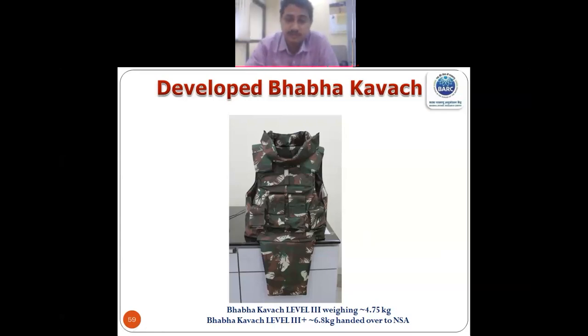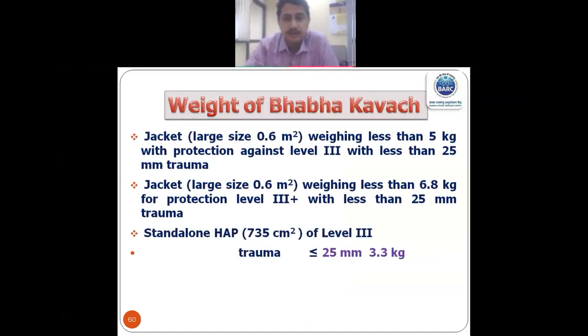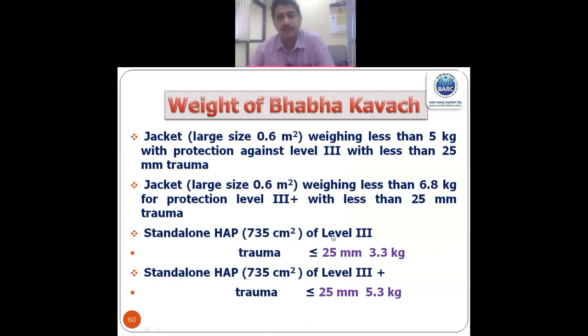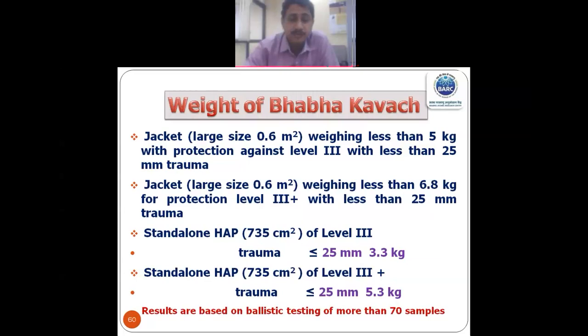So these were handed over to NSA, and this is a summary. I can show how the weight is. So we can have a less than 5 kg Bhava Kavach for level 3, and level 3 plus less than 6.8 kg. There are certain other configurations. I am not going into details. They also have very low weight and low backface signature or trauma. These results are based on more than 70 test reports and test samples, and one test means so much tumbling, so much conditioning, and 6 shots. So six shots in one test, so 70 you can understand.